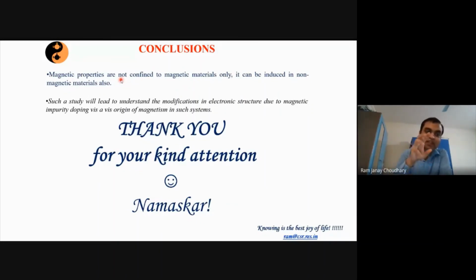Why? Because had iron metal cluster been present, iron should have shown zero charge state, which was not the case. Number one. Had this magnetization come from iron metal cluster, then we would not see the carrier mediated magnetization. How did we confirm carrier mediated magnetization? We confirmed by performing magnetoresistance measurement.